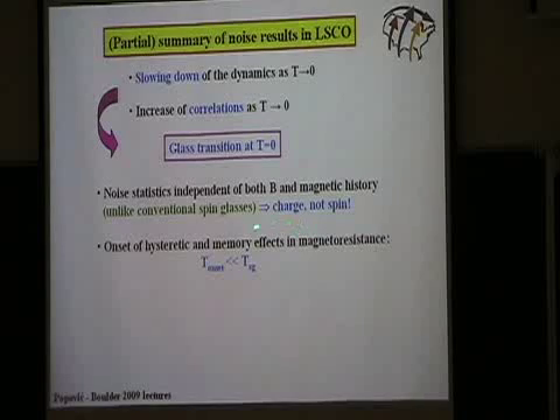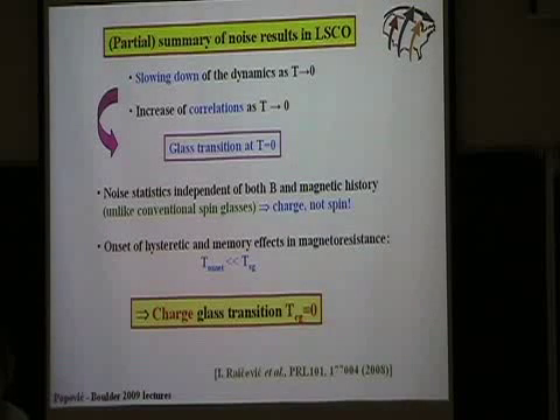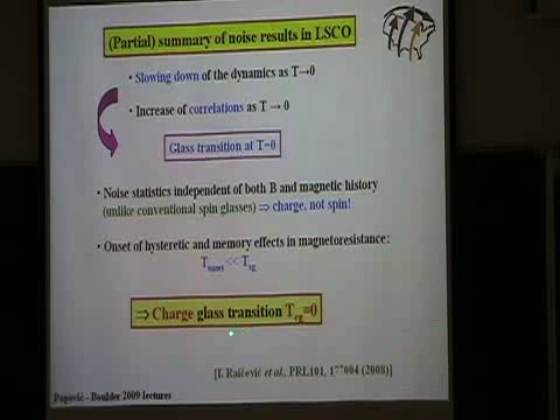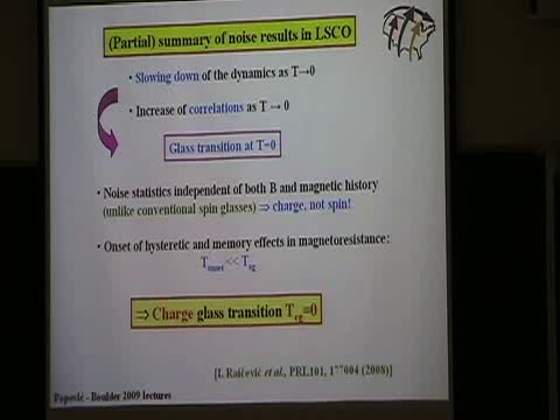the hysteretic and memory effects that we observed in magnetoresistance and that I have not shown to you also start being observable at temperatures that are much lower than the spin glass transition temperature. So all this happens deep within the spin glass phase as you go towards the zero temperature. So this suggests that here also there is a charged glass transition that occurs as a result of Coulomb interactions, and it seems to be taking place again at zero temperature.